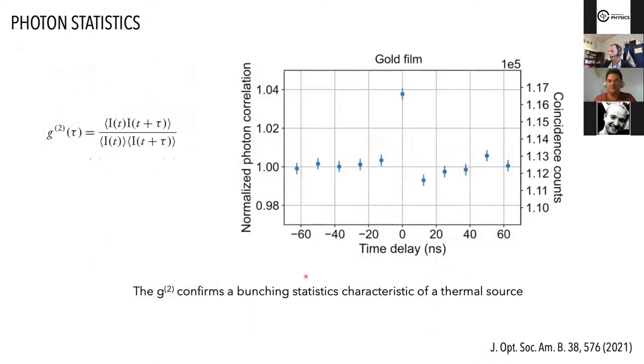The last clue that I wanted to bring is a work that has been done with Constantin, one of my PhD students, trying to measure the photon statistics of this nonlinear photoluminescence. It should not come as a surprise that these photon statistics are characteristic of photon bunching, which is expected from a chaotic light source. In our system, if it's basically thermally activated electrons that are emitting light, this is a highly chaotic source, and we expect the characteristics of photon bunching.